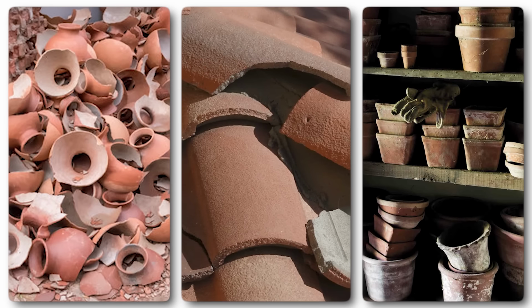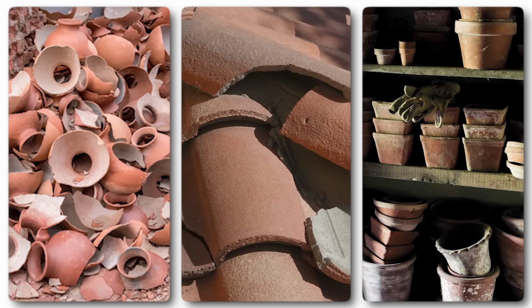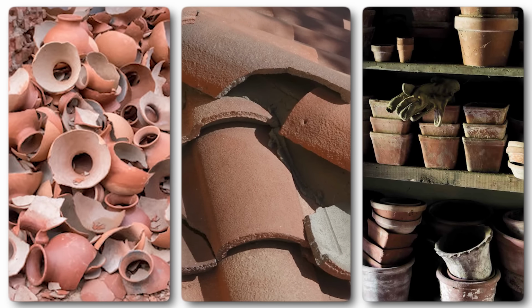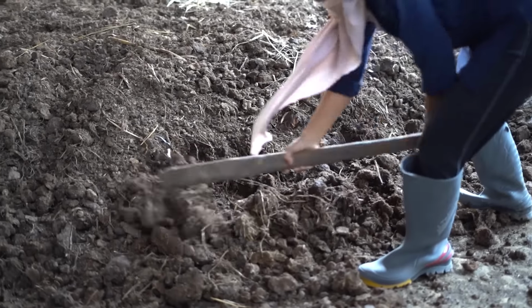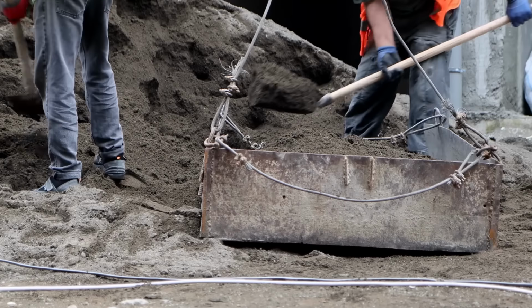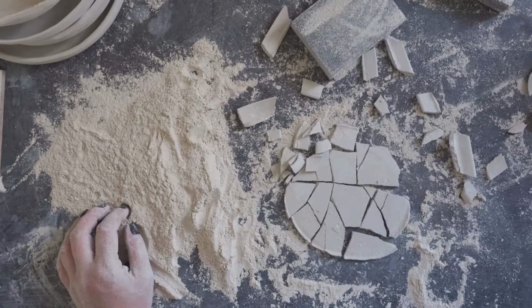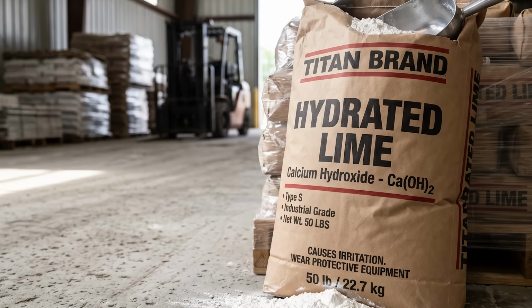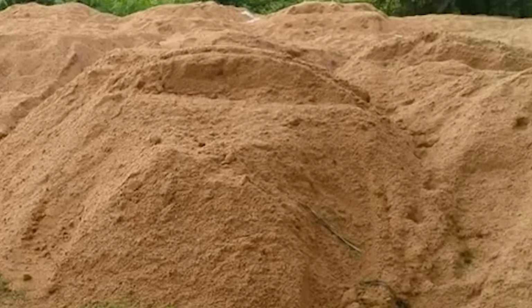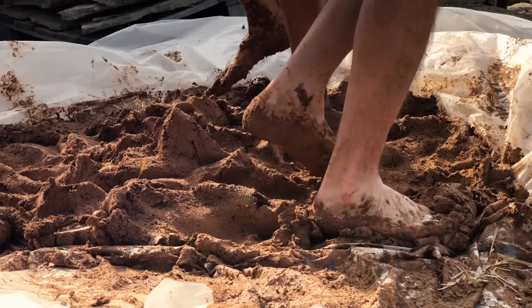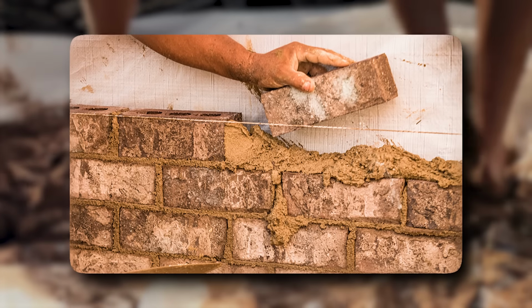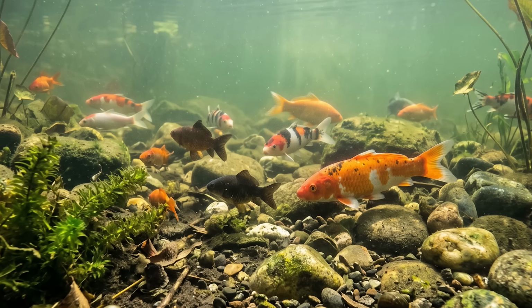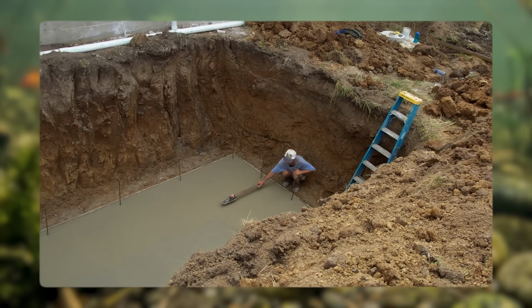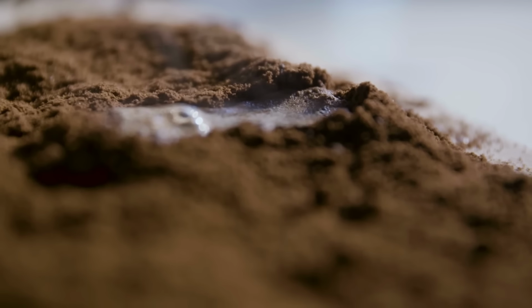Save broken pots, broken roof tiles, terracotta planter rejects. Smash them into a fine pink dust with a hammer and a heavy canvas bag. 3 parts pottery dust, 2 parts hydrated lime, 1 part sand. Mix to a stiff paste. This is the right mortar for the joints in a garden wall, the floor of a fish pond, the inside of a rain cistern. Anything that has to hold water for decades.